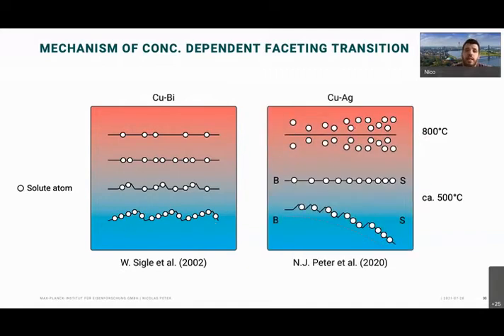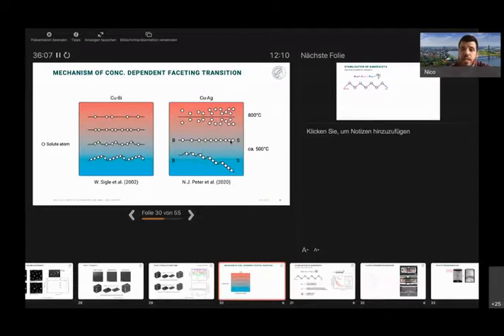We think that at high temperatures, we have the grain boundary and silver in solid solution with higher concentrations towards the surface. So the right side is the surface, this is the bulk. So if we cool now, all the silver slowly starts going towards the boundary, segregating towards the boundary, at higher concentrations at the surface to lower concentrations in the bulk. And then they initiate the facets because it's energetically favorable to initiate these 210 segments. They take up more silver, they lower the energy further, so it makes sense to nucleate them.